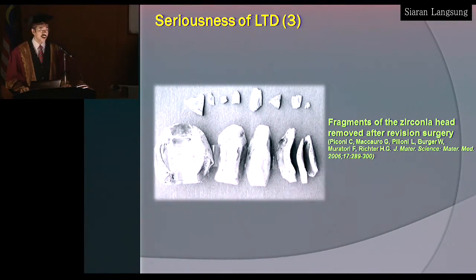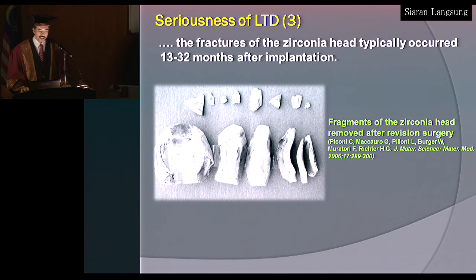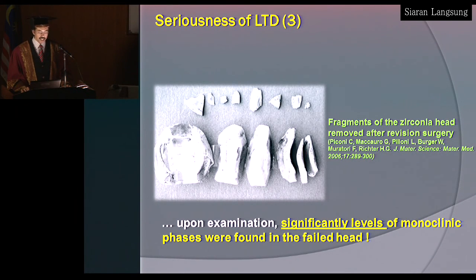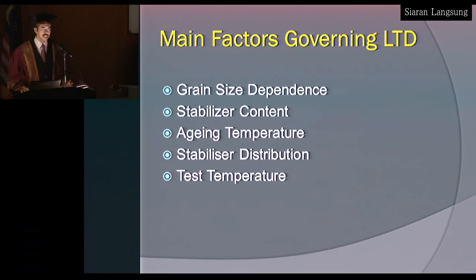And this has an effect on the manufacturers because fracture of the head has been observed after 13 to 32 months of implantation. Close examination of these fractured femoral heads revealed high monoclinic content. So phase transformation has taken place at body temperature, over a period of 13 to 32 months. So what are the factors governing LTD? These are the main factors: the tetragonal grain size, the stabilizer content, the distribution of the stabilizer, and the test temperature.